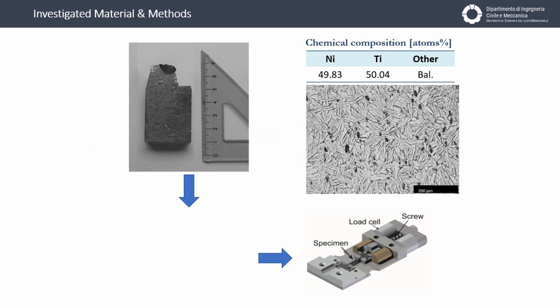The product of the casting is the ingot. It's a very short ingot. The height is around 5 centimeters, and the material has been characterized both in terms of the chemical composition. You can see that the quantity of nickel and titanium in atoms is quite similar, and in terms of microstructure, you can see the magnification. This is around 500 times magnification.